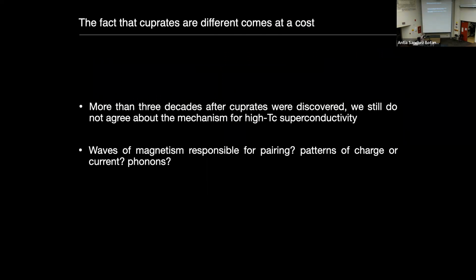But of course, that comes at a cost. And the cost is that more than 3 decades after their discovery, we still do not fully agree in terms of what is at the origin of high TC. There are very good ideas, but I would say there is not a quantitative theory yet. So there are people that say that it's waves of magnetism that are responsible for pairing, playing a similar role to the one that phonons play in the conventional superconductors. Others say that it's patterns of charge or current or even phonons that actually play the key role, and it may even be a combination of all of those.